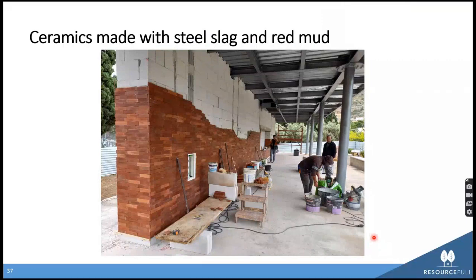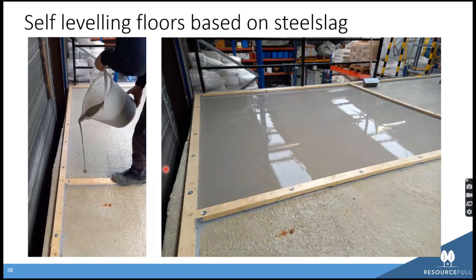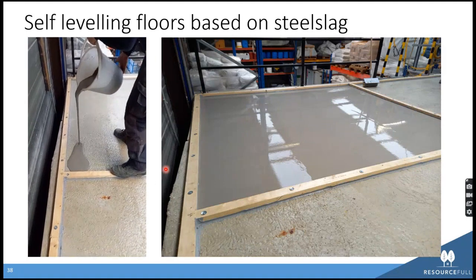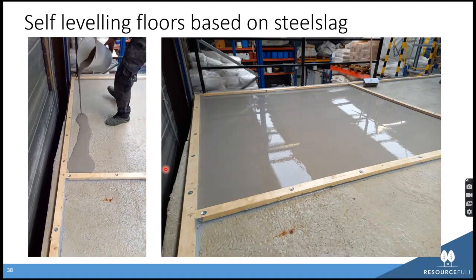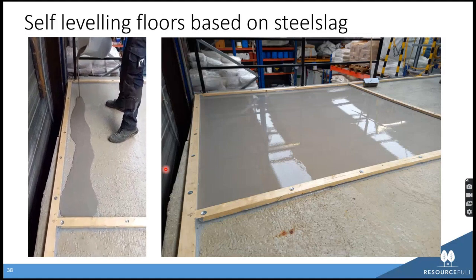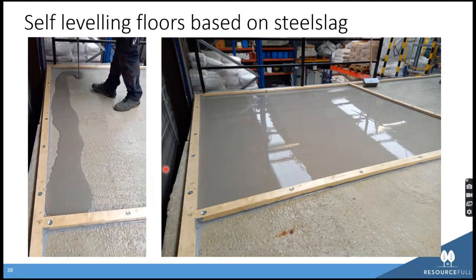Brick slips, baked clay, has also a very high footprint, although it's not known for that, but it has a higher footprint than concrete, for example. And this is something that can be implemented quite fast because it's not structural, not reinforced, and so forth. Self-leveling floors, a little bit the same, decorative layers, but we get out all the Portland cement and we do it purely based on steel slag.